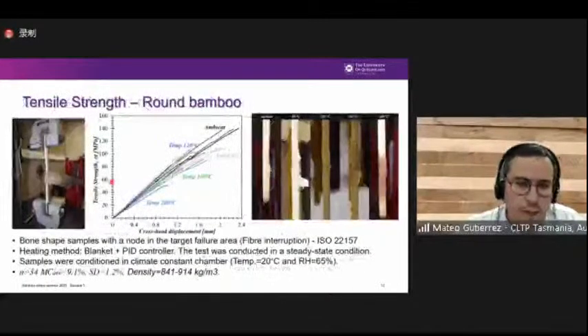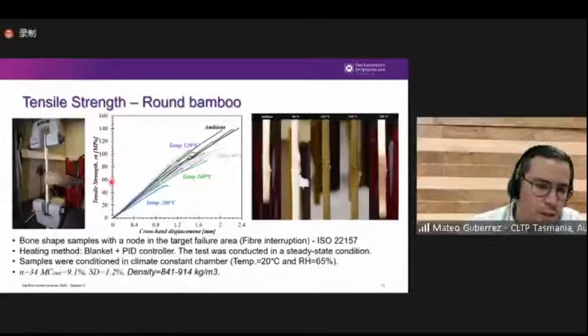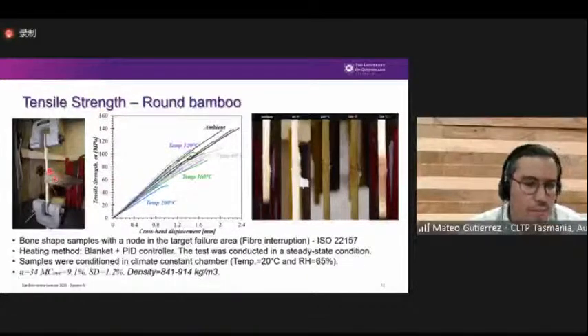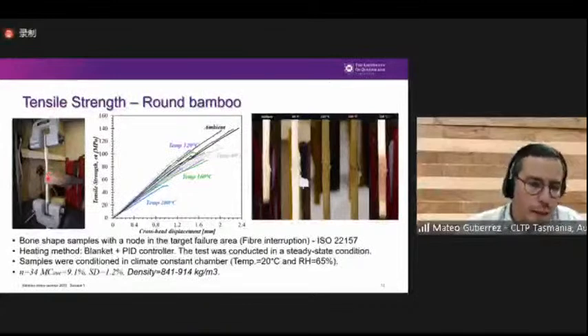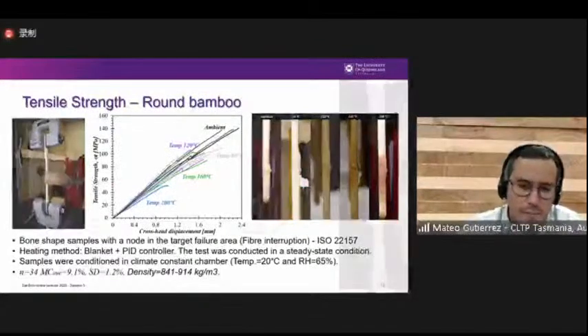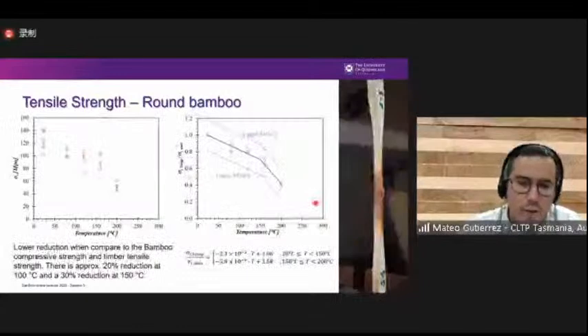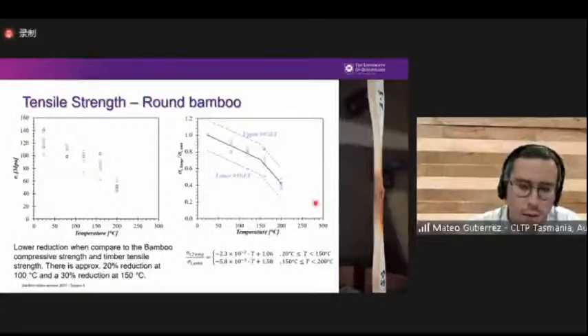Then we conducted the tests to understand the tensile strength. Instead of using an environmental chamber, we ended up using a heating blanket. We knew that our samples were going to fail at the midpoint, basically where the knot is located. So we heat up that area, and then we look at the reduction of the tensile strength and look at the failure modes.